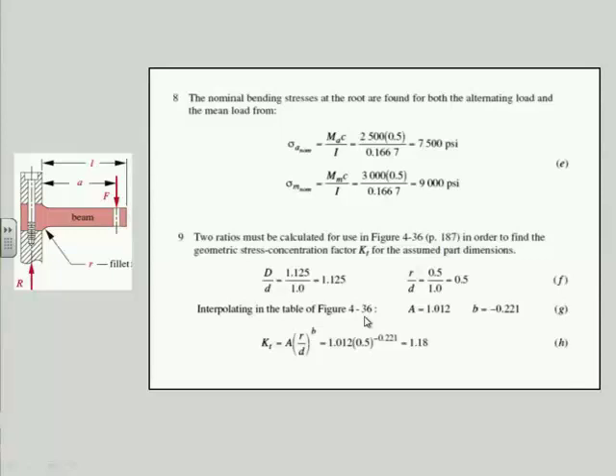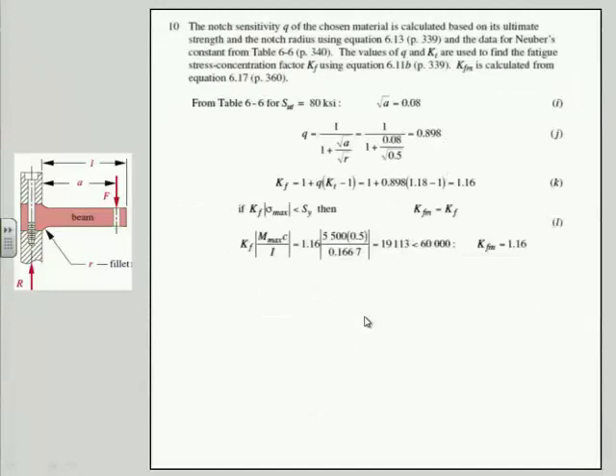And in that chart, I find I don't happen to have an entry for 1.125 for the D over d, so I interpolate between the two neighboring values in the chart, and I get a 1.012 for the A, which is the coefficient, and I interpolate to get this 0.221, put it in my fitted curve, and out pops 1.18. Not too bad. A nice big radius, so I've got a fairly low stress concentration. Now that's the Kt, the so-called geometric stress concentration factor, which is what we would use for a static case. Just stop right there. But this is a fatigue case, and I want every little bit I can get.